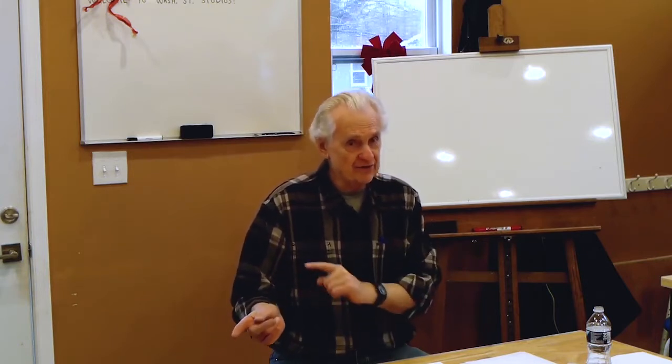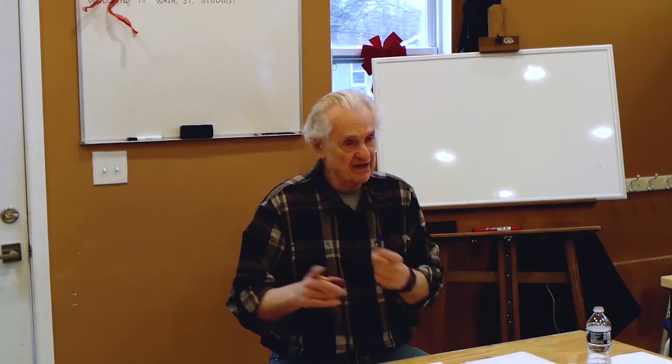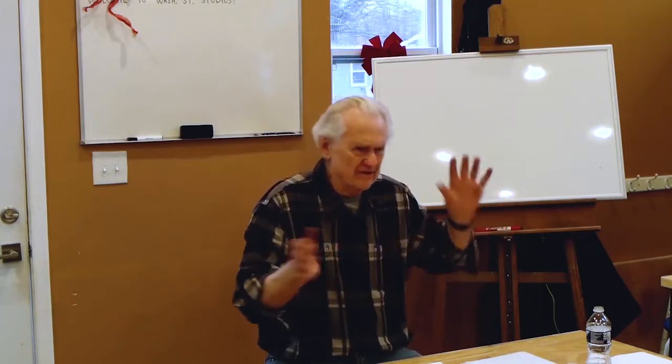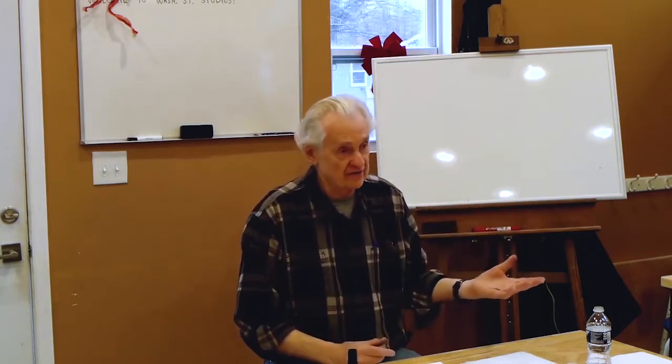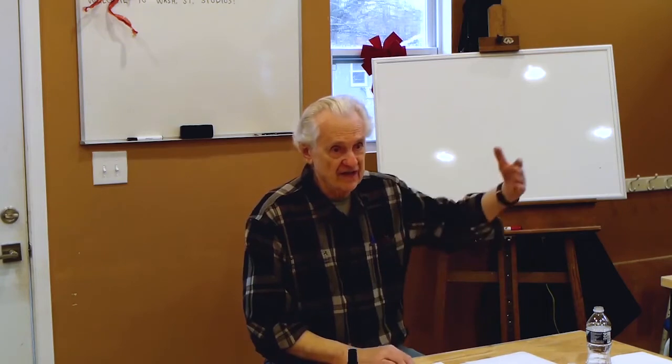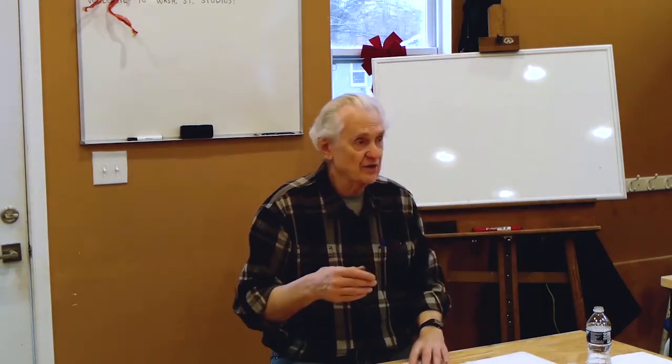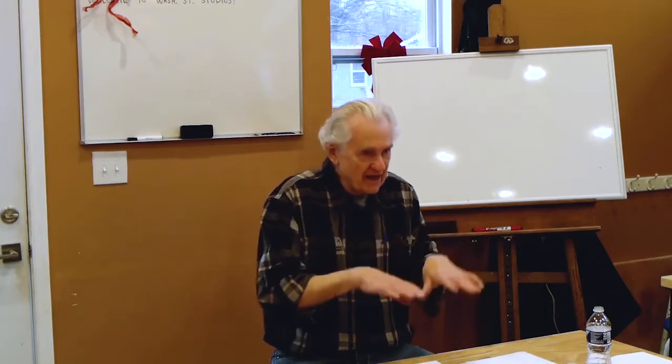So it may not show up during the drying. It may not show up during the bisque. But it probably will show up at the very end, during the glaze firing. And you've lost the continuity of, well, where did this piece come from in the slab? Forget it. But that's the cause. You used an edge piece from the slab. So there's a case where, even though I'm applying compression and shear, I create tension on the edges, and that can lead to cracking.